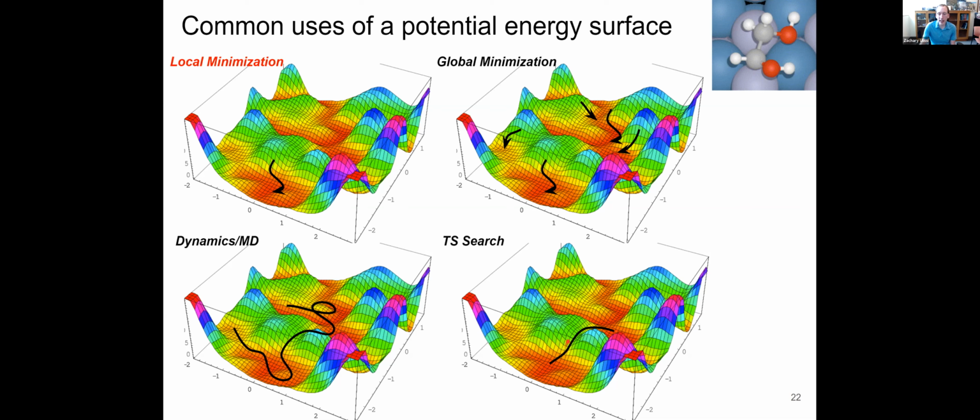Another important point here is that in catalysis, we use these things called linear scaling relations a lot to simplify our lives. But often the most interesting materials are the ones that don't obey those scaling relations, the ones that are outliers. And so we have to be a little bit careful if we make too many assumptions. There could be a different mechanism for specific types of surfaces that we missed, and those are sometimes the most interesting ones. And so that makes our lives a little complicated. Even if we could guess it 90% of the time, the 10% of the time where we couldn't guess it might be the most interesting ones that we should really drill down on.